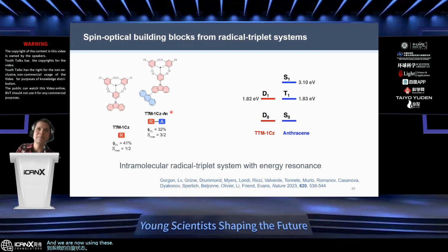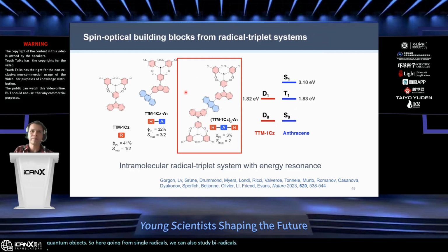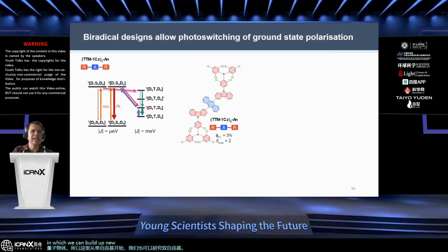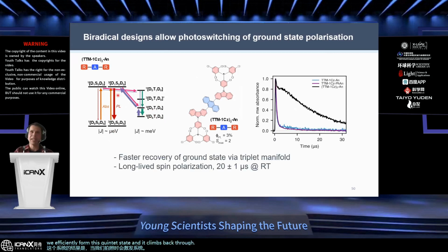And we are now using these systems to create building block quantum objects. Going from single radicals, we can also study biradicals, in which we can build up new Jablonski diagrams now with quintet, triplet, and singlet states. When we photoexcite the system, we efficiently form this quintet state, and it climbs back through the triplet channel, which you can imagine a little bit like a light switch. You photoexcite the system, you form this high spin state, and then it returns back to the ground state with all of the electrons lined up in a spin polarized way, which was an exciting result for us at room temperature.